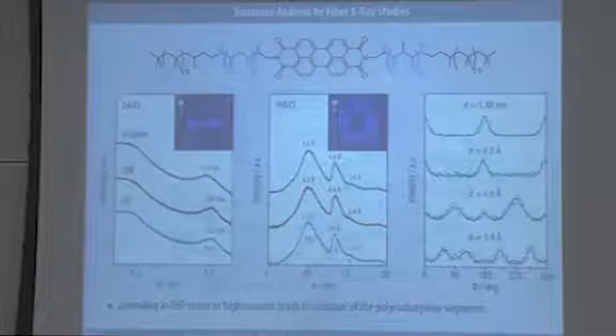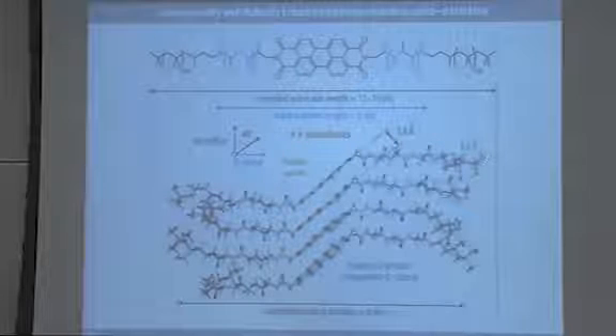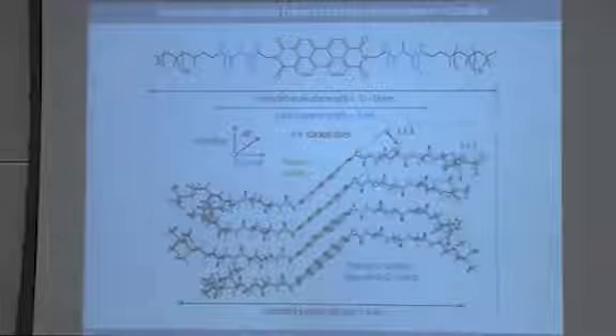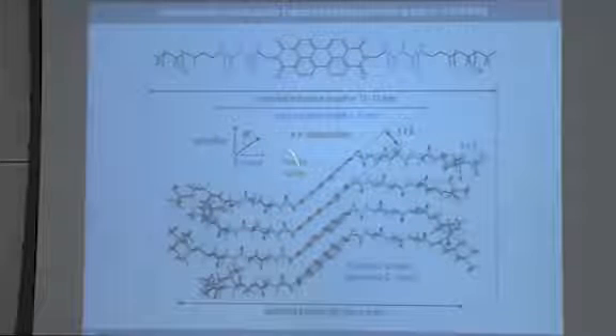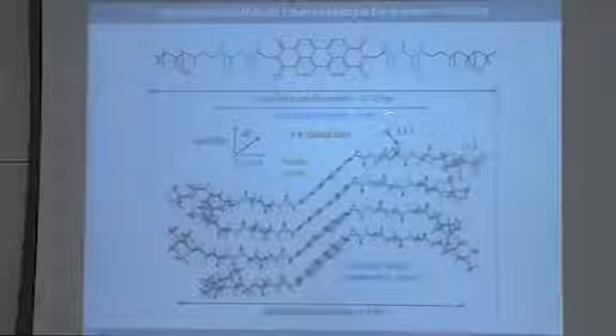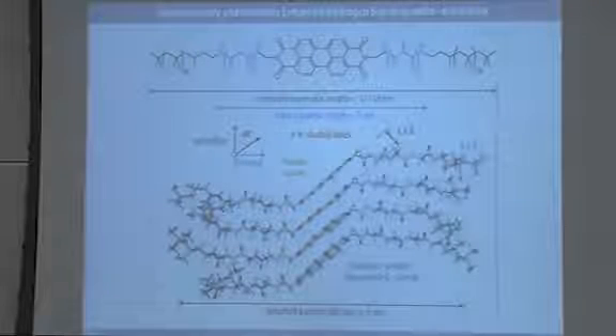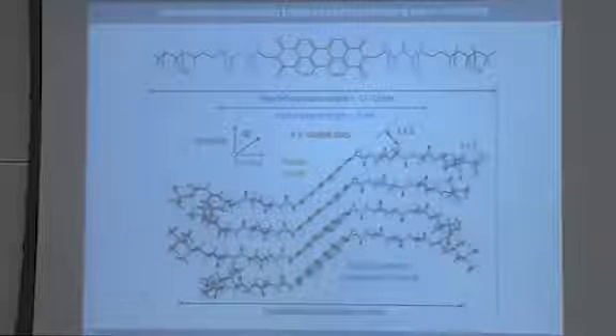And this is trigonometrically very consistent with a picture that looks like this. So if you have a stacking distance of 4.6 angstrom of the oligopeptides, and an angle of the quaterthiophenes of 48 degrees with the microfiber axis, then the pi-pi stacking distance that you derive from that trigonometrically is 3.4 angstroms. In the case of the oligothiophenes, it's 3.5 angstroms. And that is very well consistent with the data we actually obtained from the X-ray.